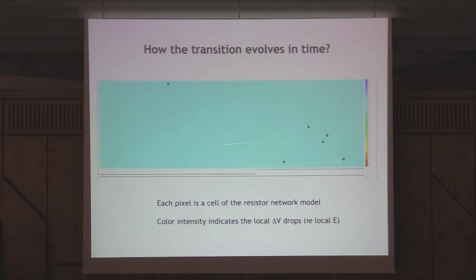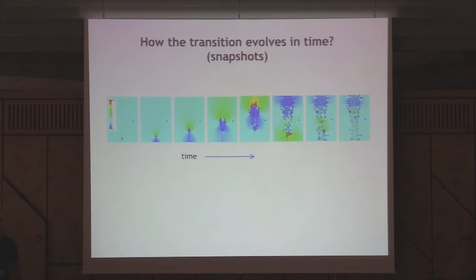You see that you get some sites going metallic, you get some sites going metallic, but suddenly you have a nucleation of a little segment. That little segment produces a very strong field at the head and makes this grow. So in order to see this clearly, these are snapshots of what you just saw.